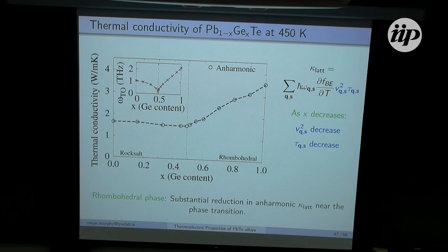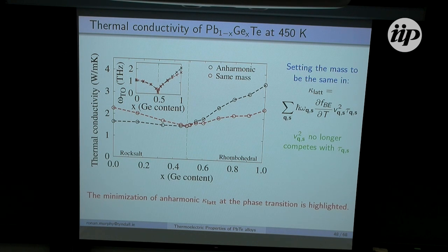So if we do a little thought experiment and imagine our alloy as, say, each composition having the same mass, we get this red curve here. I will just mention here in the top left, this black curve is the TO mode frequency at the gamma point where each alloy composition has its own mass. And then red is where I've renormalized these masses to be the same. And you see that while there may be a slight difference here and here, more or less they are the same curves. So it's showing that as we get nearer the phase transition, it is just that and not, say, the mass difference that is reducing our TO mode frequency.